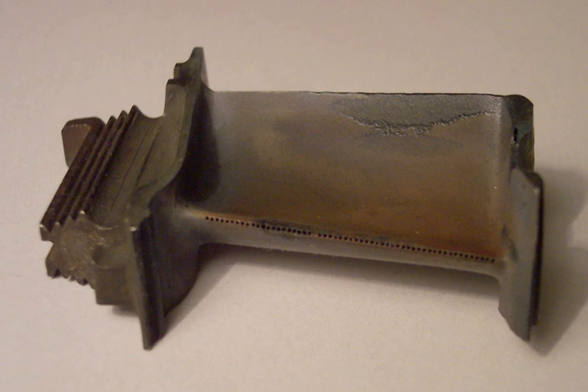Superalloy products that are subjected to high working temperatures and corrosive atmosphere, such as the high-pressure turbine region of jet engines, are coated with various kinds of coating. Several kinds of coating process are applied: pack cementation process, gas phase coating, both of which are a type of chemical vapor deposition, CVD, thermal spraying, and physical vapor deposition. In most cases, after the coating process, near surface regions of parts are enriched with aluminium, the matrix of the coating being nickel aluminide.